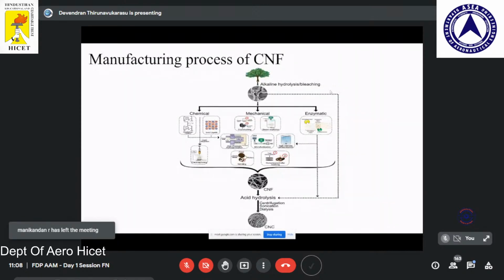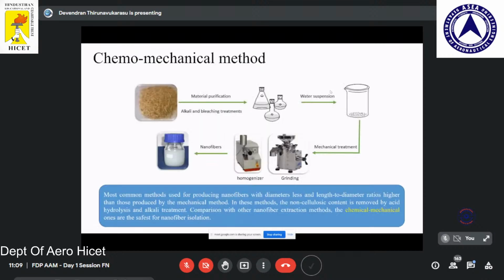And this is a process from the tree or plant. We are doing alkaline treatment and hydrolysis. Then we have 3 different processes: mechanical, chemical, and enzymatic. Here we use the mechanical process. We are drying and crushing, and doing the pulverization, the nanopulverization process. Then we can get the cellulose nanofibers. With further hydrolysis, it is also possible to make cellulose nanocrystals. And this chemical-mechanical method we developed: after the alkaline treatment, we disperse it in water suspension. With grinding and homogenization, we can get a nanofiber suspension like this.